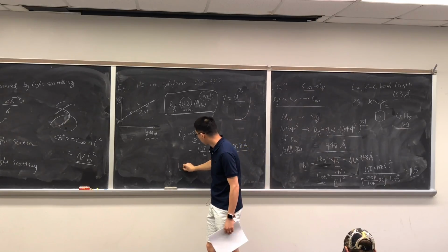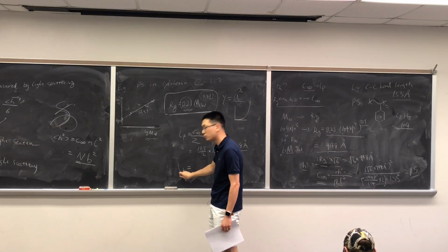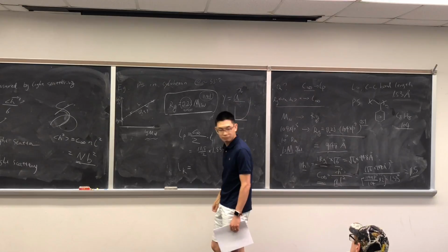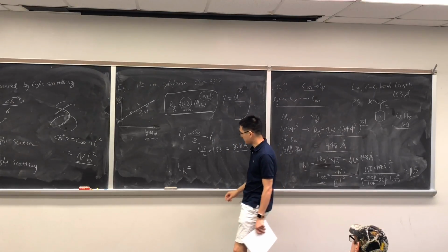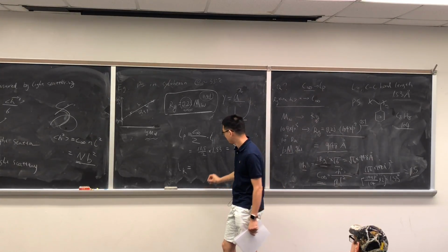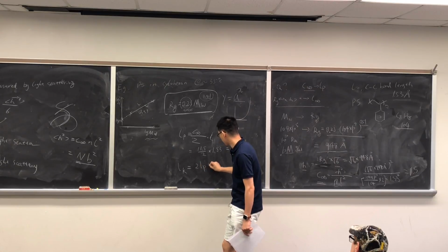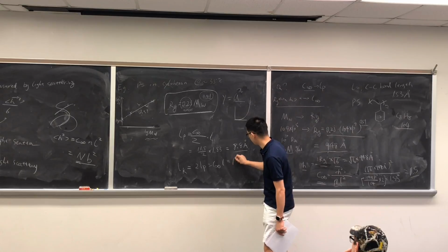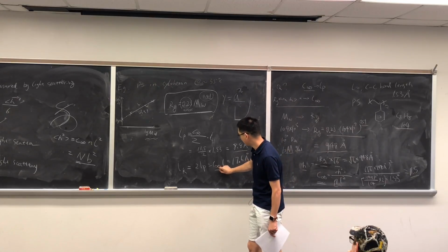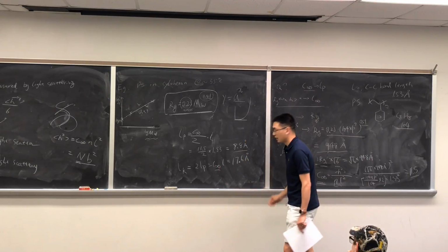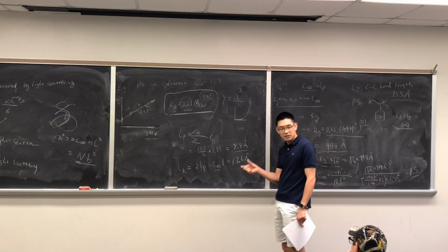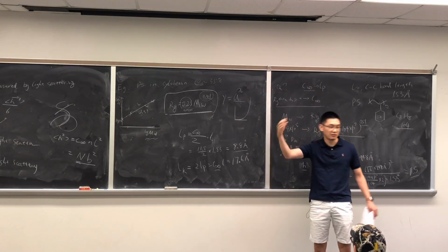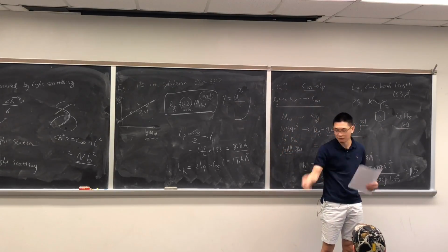And there's another parameter, LK, or Kuhn length, which is another definition with 2LP. So this is just C infinity times L. This is roughly twice of that, so 17.6 angstrom. So in other words, it takes about 11.5 monomer or chain carbon-carbon bonds, then your chain can fold back to 180 degrees.